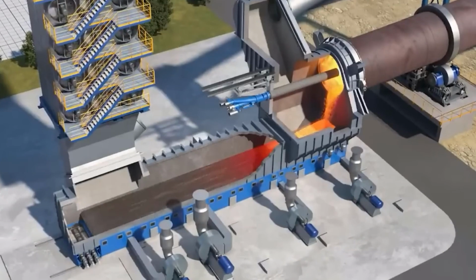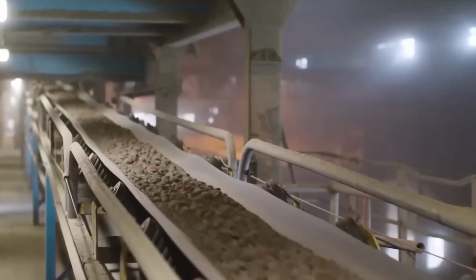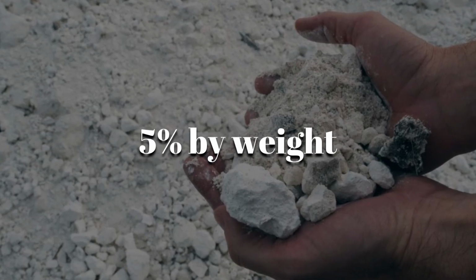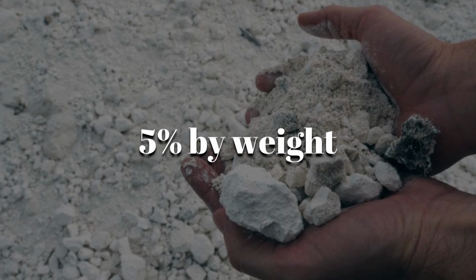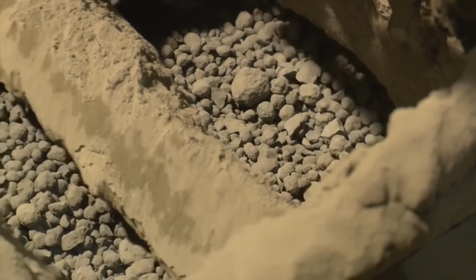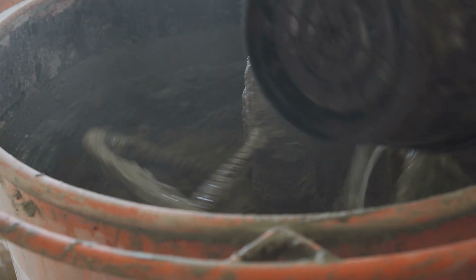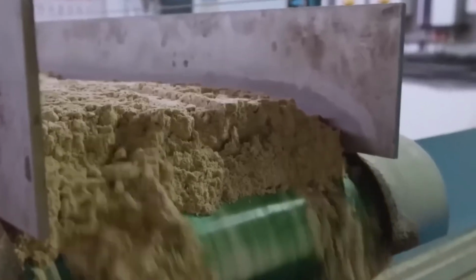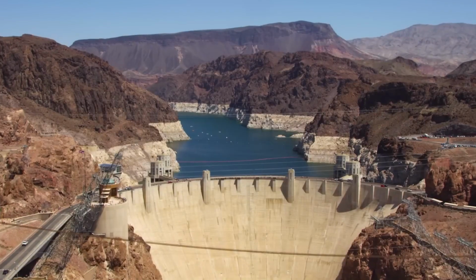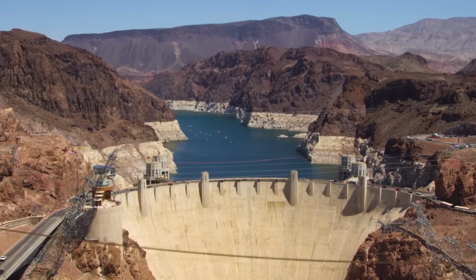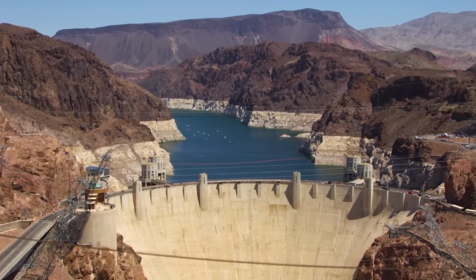project on schedule. After cooling, the clinker was sent through grinding mills where it was crushed once more and combined with a small amount of gypsum, around 5% by weight. This final touch was crucial because it controlled how quickly the cement would set when mixed with water. What came out of the process was the fine gray powder we recognize as cement, ready to be used in one of the biggest construction projects the world had ever seen.